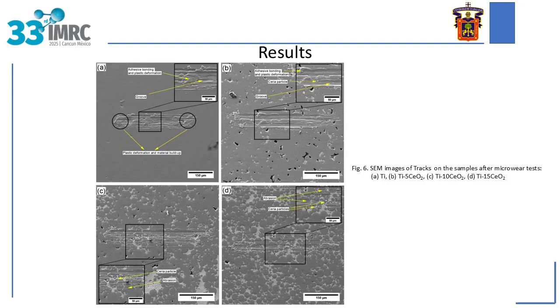In the case of the titanium 5 ceria composite, the footprint height and the areas with adhesion and plastic deformation decreased due to its greater hardness compared to the matrix. In the case of the materials with 10 and 15% reinforcement, the dimension of the traces continues to decrease, and they are not even well defined, because the areas where ceria is present apparently suffer minimal wear. Additionally, the presence of fewer zones exhibiting adhesion and plastic deformation is notable, along with the observation of isolated grooves likely resulting from detached ceria particles during the sliding process.